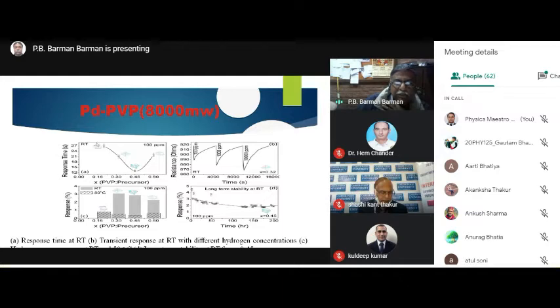We can see that this is at room temperature, and whatever the best response time we can see is at my 100 ppm. We have done the same experiment at 50 degrees centigrade also, but you can see the response is not good - the response is not good.